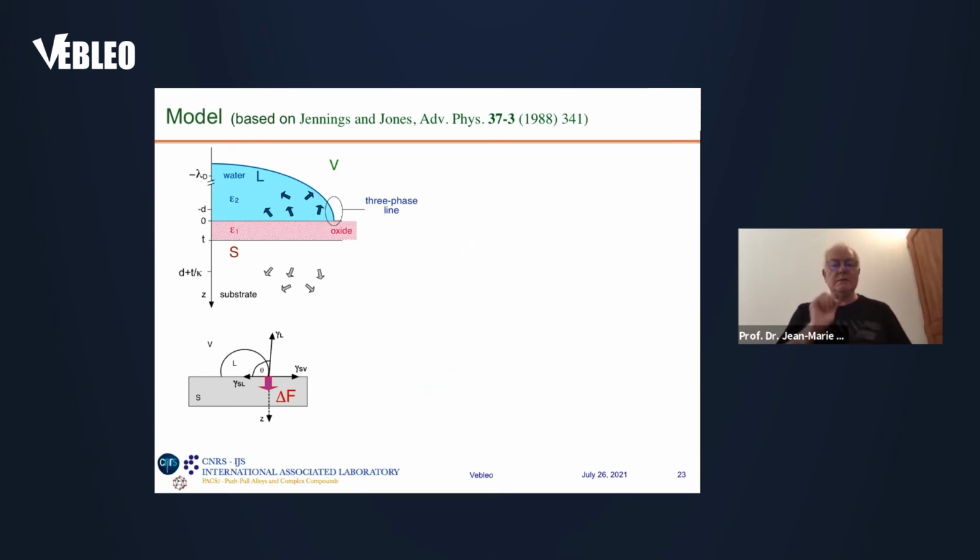So this can be modeled. I will not go into the details of this model, but it is based on the formation of dipole images in the sea of Fermi electrons inside the quasicrystal under the oxide, which is just an inert spacing. And this interaction between dipoles on the water molecule and image dipoles determines the strength of this force, which must be included to reach equilibrium.